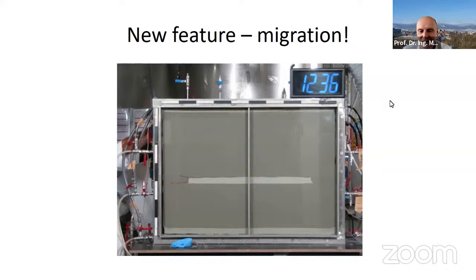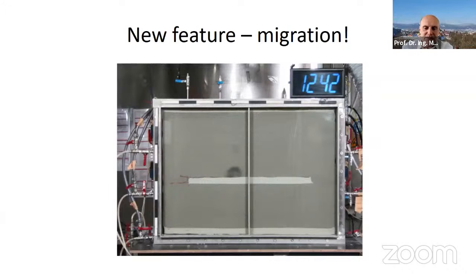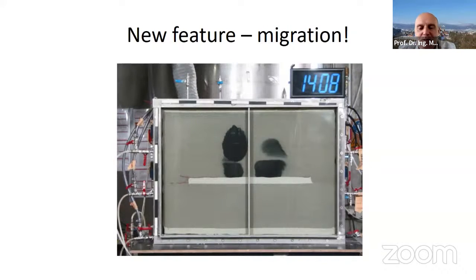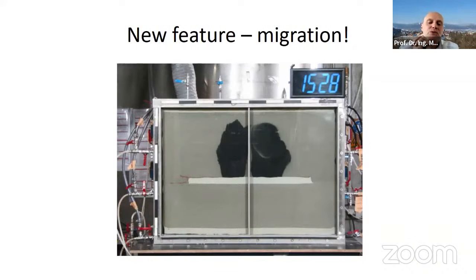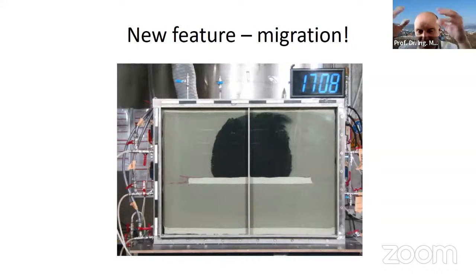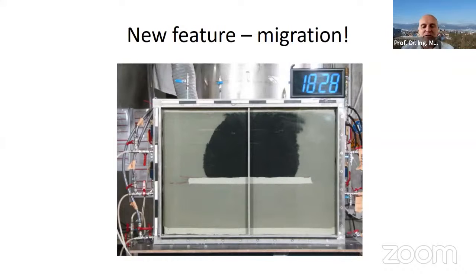This is one more picture from the laboratory, where we have an aquarium about 2 by 1 meter, where from the back we inject the nanoparticles, and you see how the nanoparticles are moving in the soil, so they are really able to move. And this is, as I said, the basic advantage of these particles compared to microscopic particles, that they are able to move and to react with contaminants which are distant from the injection well.